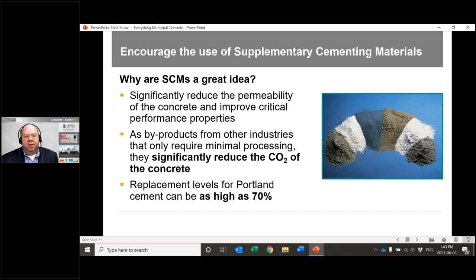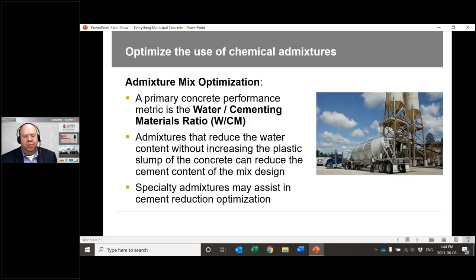So again, when we get into mass concrete elements, like if we're doing let's say a 2 meter base slab for a downtown condo that's going to be 40 stories high, again, there's a great application for 50, 60, 70% SCM usage, because again, you've got a really thick layer of concrete that's going to generate a lot of heat. That heat's going to be a problem, so that's another reason to use SCMs, but it's really going to reduce the carbon footprint of the concrete. So we need to look for those optimization challenges.